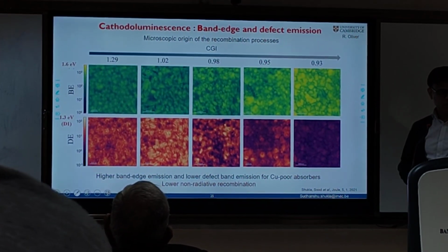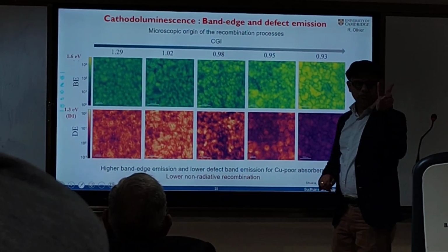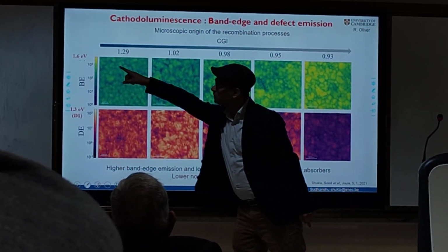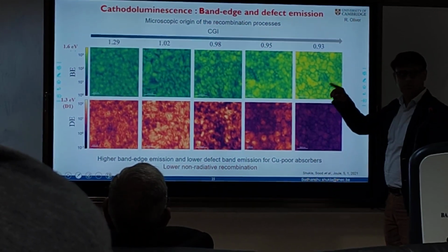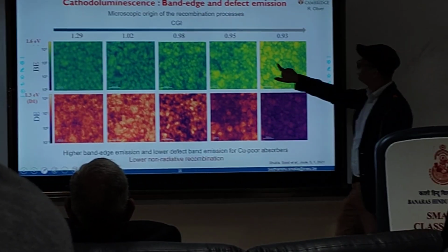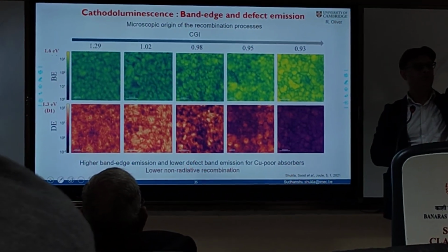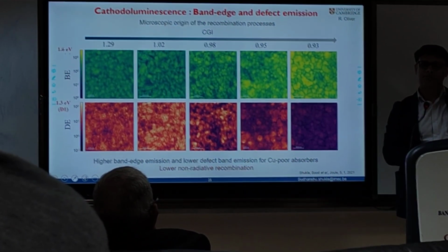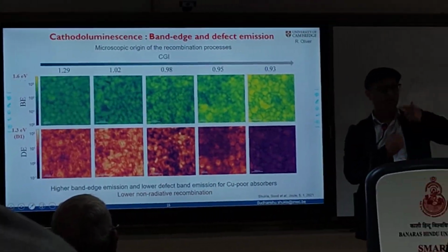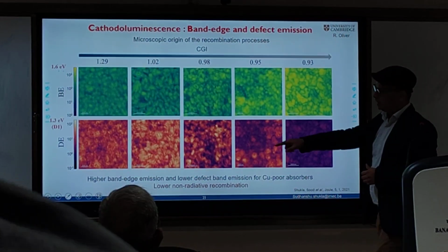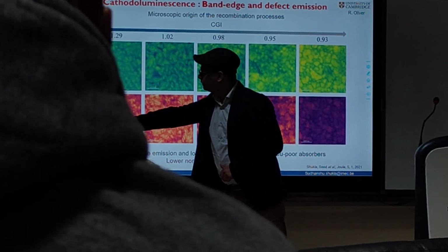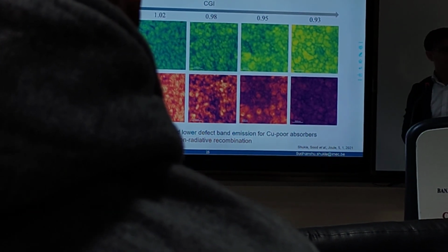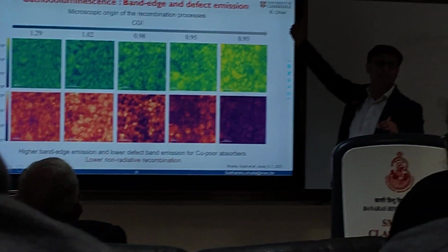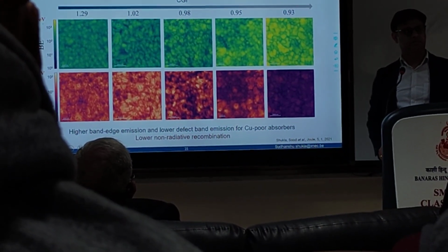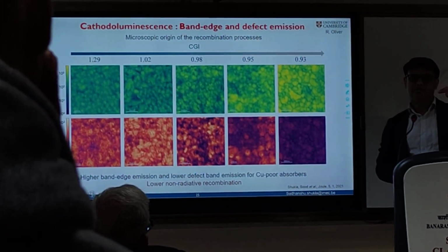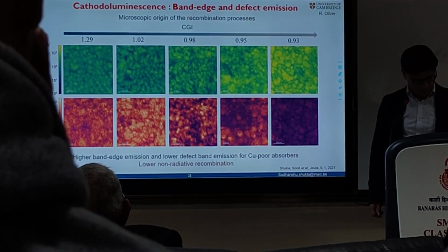Let's look at it pictorially. We also did mapping. Let's say there were two emissions. One was the band edge emission at 1.6. If you do spatial mapping, you see that when you go from copper rich to copper poor, they get more intense. So your band gap signal improves, which means the quality of your sample is becoming better, because PL is an indicator of quality as well. You have less recombination essentially. At the same time, if you look at the defect emission, which is the D1 defect, remember, as you go from copper rich to copper poor, it gets lower. So your defect reduces, your band edge emission increases. That's an indication that you suppress recombination. That's why you have higher band gap luminescence, but less defect emission. So this is a very consistent picture.